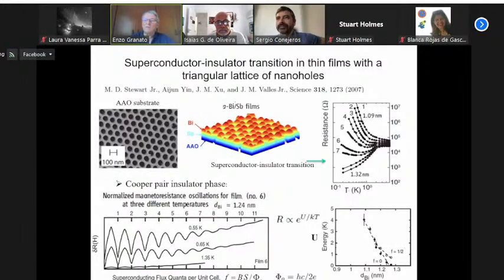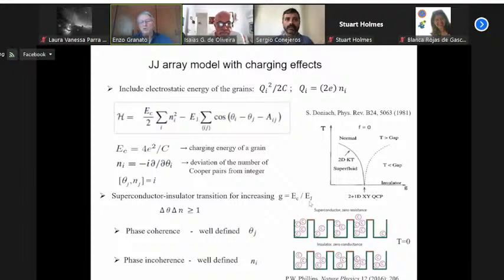If you take a superconducting film and you decrease the thickness, eventually it becomes an insulator. That's one way of thinking. In terms of this modeling, it's just because the charging energy increases. Actually, the transition depends on the ratio of the charging energy divided by the Josephson coupling, right? So you can either approach the transition by changing the charging energy, decreasing the grain size, because this increases the charging energy, the capacitance decreases. Or you can also approach the transition by decreasing the Josephson coupling.